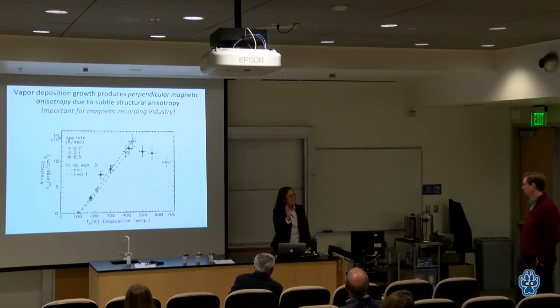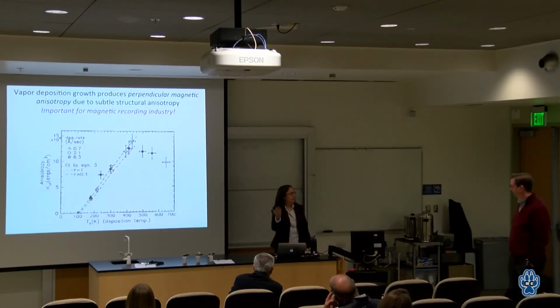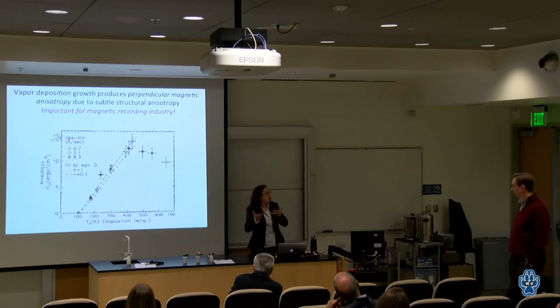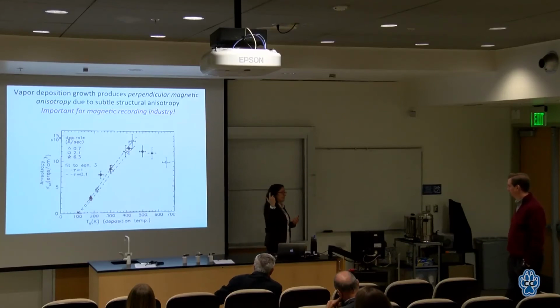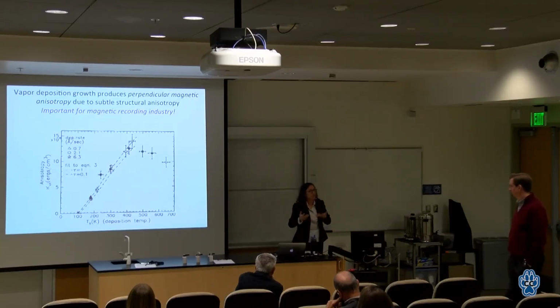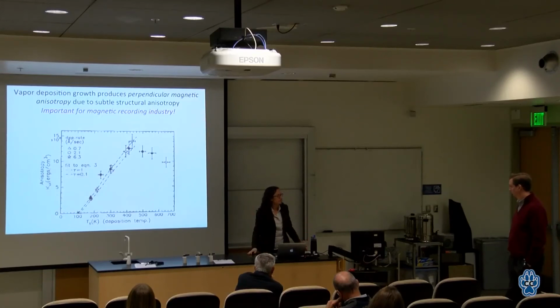But the out of plane is a big deal, and the only way you get, just as was being asked before, shape anisotropy puts everything in plane. So you have to have something that pulls it out of plane, and usually people think of making that be the crystal structure. So they go to a lot of trouble to grow c-axis HCP cobalt with the c-axis out of plane, and that has a reasonably large perpendicular anisotropy. So everybody was rather surprised when this material that's amorphous has a perpendicular anisotropy that's actually at least as large as a material you've deliberately grown crystalline, deliberately grown with a c-axis out of plane, and here you have this blobby mess which has just as big an anisotropy.